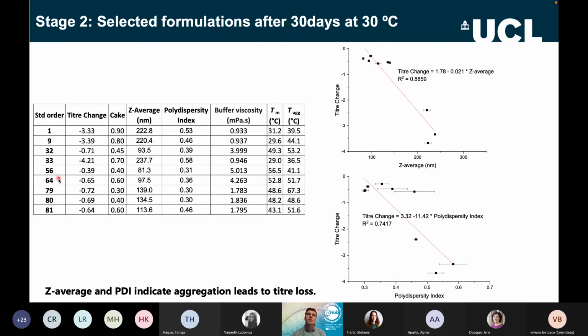So we took some of those formulations shown here by their order number, and we measured using DLS the average particle size, the polydispersity index, which is an indication of how many different peaks you've got in terms of different sizes. And we also measured the viscosity of the solution to see if that was having a major impact. We measured their melting temperatures and also their aggregation temperatures once reconstituted. This is all reconstituted after initial freeze drying.